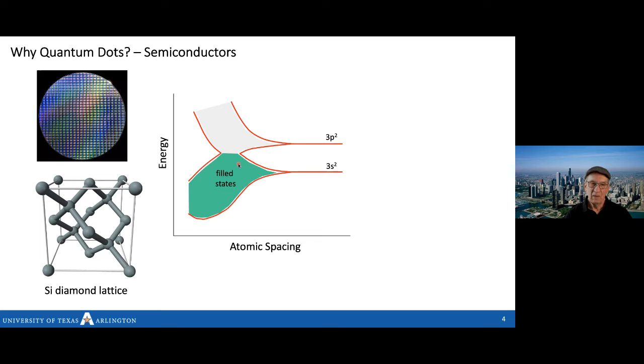Well, there's a natural place where silicon forms the diamond lattice structure, called the diamond lattice because it's the same as diamond. They're one above each other in the periodic table. And when it reaches that stable point, it builds a very strong tetrahedral bond. So there are four bonds with each silicon atom, four strong covalent bonds with nearest neighbors to complete the outer shells of all of them by the shared electrons from the covalent bond. So that point actually takes place at a lattice constant of a little over a half a nanometer.